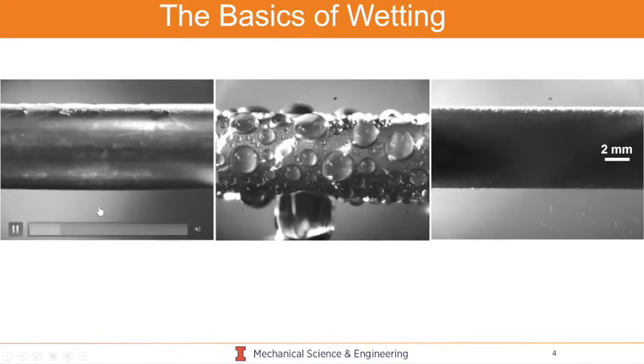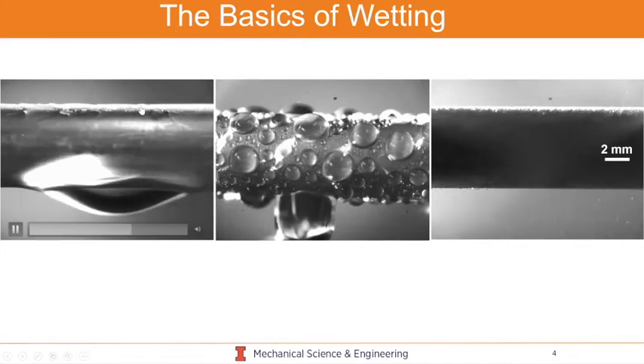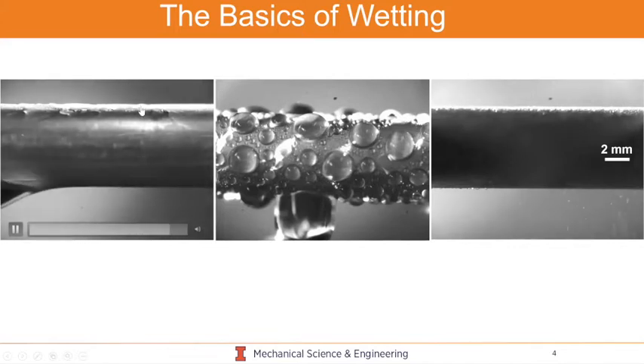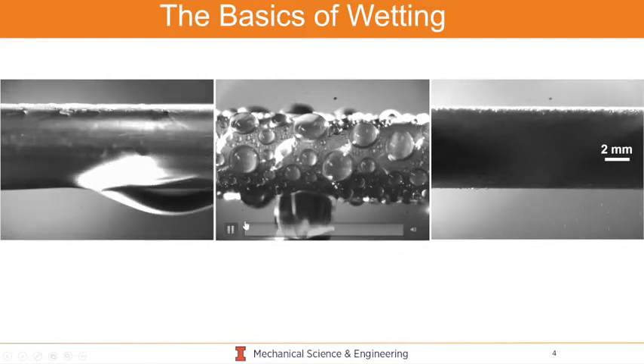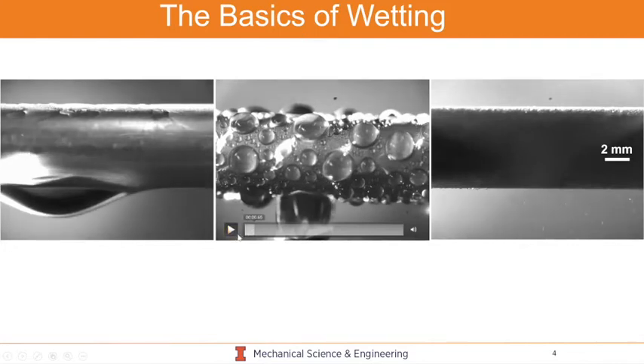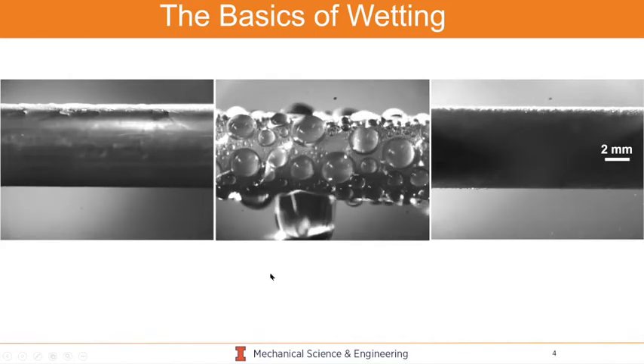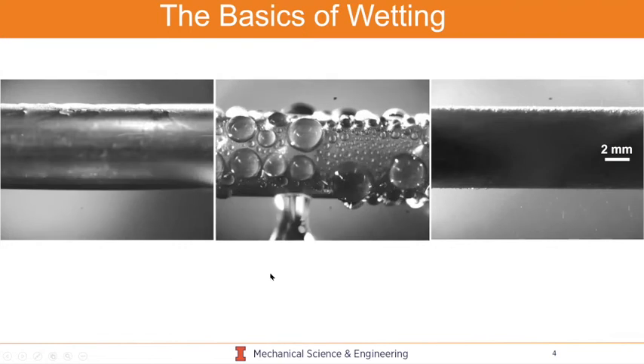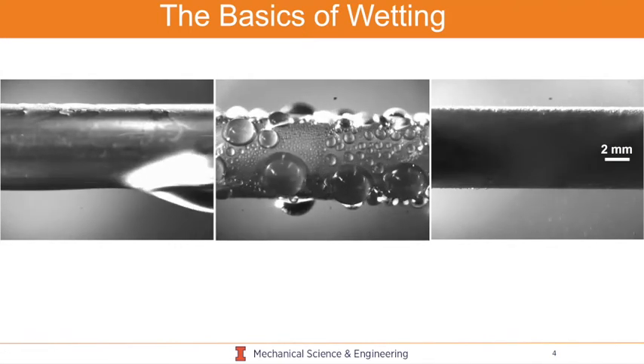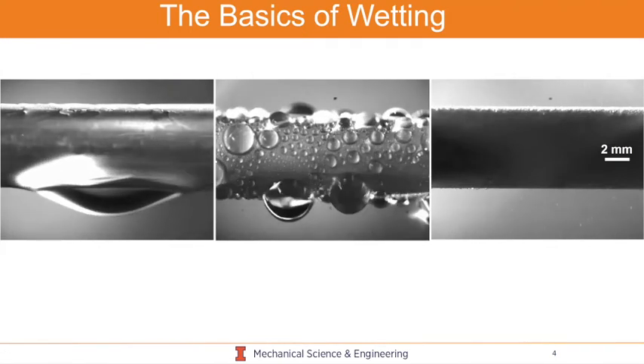Now, if I told you you could add a one molecule thick layer, so you're adding 1 nanometer of thickness on top of this tube on the outside, this is actually what will happen. So you'll actually start undergoing dropwise condensation. And so in terms of bang for your buck, the amount of material that you're actually adding, you're only tailoring the interface.